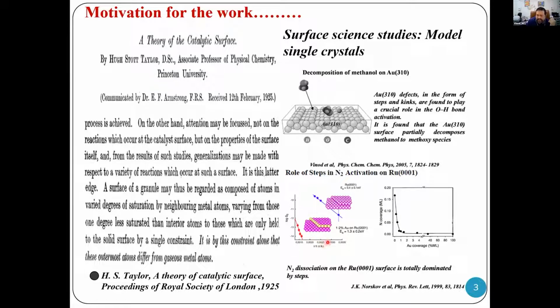There is several other work which has come in the literature, and one particular paper that needs attention is the activation of nitrogen, because nitrogen activation is one of the holy grail problems in catalysis. Looking at it with a surface science perspective, this group with Nørskov and Chorkendorff in Technical University of Denmark identified that the step sites present on ruthenium are the active sites for activating nitrogen. If you try to block these sites with a poison like a gold atom, then the activation barrier is very, very high for the dissociation of the nitrogen molecule. It's a very nice, interesting piece of work that was published in Physical Review Letters in 1999.